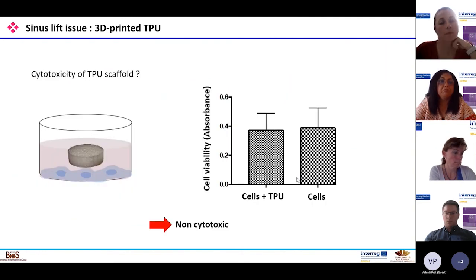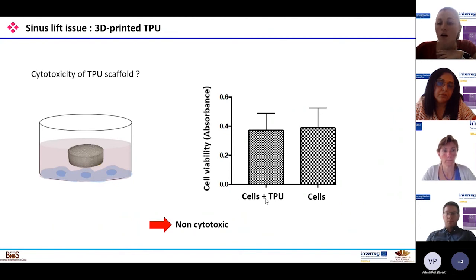The first step here was, of course, to check the cytotoxicity of the scaffolds. For that, we seeded some cells in a plastic culture plate, and we put the scaffold in contact. We checked the cell viability, and we observed that the presence of the TPU scaffold had no impact on cell viability, so the scaffold was not cytotoxic.